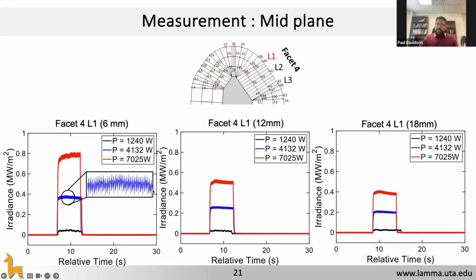And then if you look at the measurements which we get, you can see that for a given power, so we looked at three powers, 1,240 watts, 4,000 and 7,000 watts, for any given reading, the value of incident radiation is not a fixed value. And we are pulsing the light at a given frequency. Because of that, you get these very high oscillations in your incident radiation itself. But on an average, the values are fairly smooth, right? So depending on how far you are from the quartz facet, you can get different values of incident radiation.